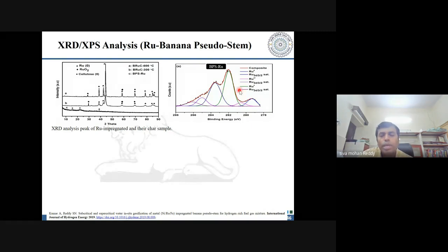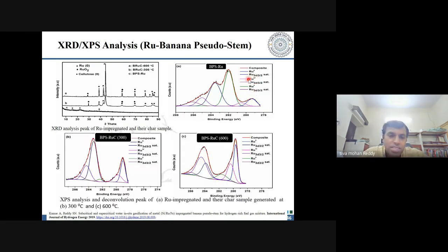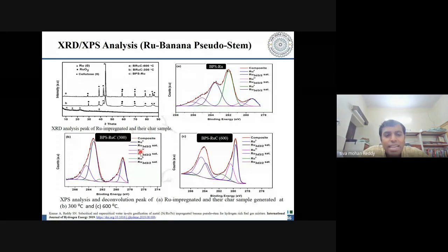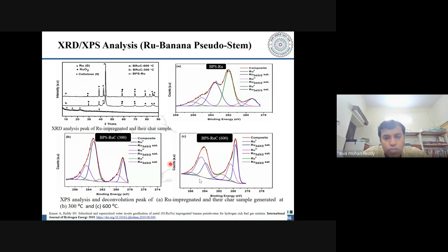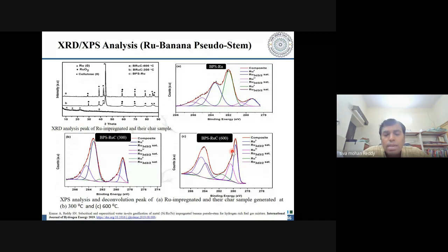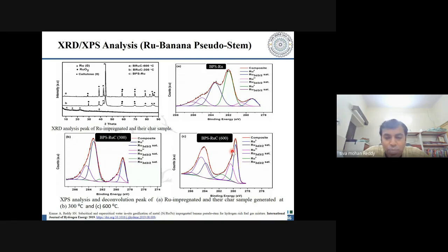ruthenium also existed in the +2 and +4 forms during as-impregnated state. Now even at 300 degrees centigrade, we see that ruthenium existed in all the three forms, that is, in the ruthenium metal form and also in the +2 and +4 forms. But whereas if you see at 600 degrees centigrade, the intensity of the blue peak is enhanced, which conveys that the reduction of your metals is happening at the supercritical conditions that we are using, that might be from the carbon source or from the reaction medium itself.